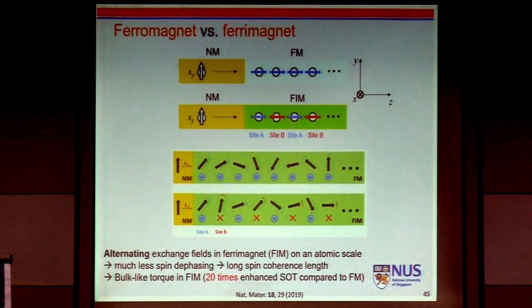But anyhow, we now try to combine this ferrimagnetic concept with the superlattice. And the superlattice has been widely used in many areas like optoelectronics and so on. And then we show that by having this superlattice, once you inject the spin, initially you dephase your spin in the cobalt layer. But in the next layer, the rare earth layer, we recover its spin. It's like a spin repeater concept in fiber communication technology.